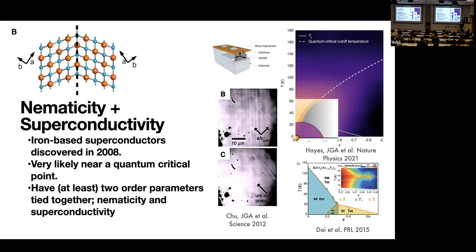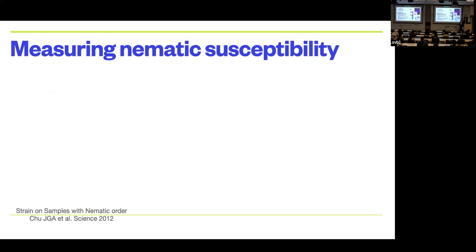But anyway, what was the broken symmetry? What was the order parameter? Well, we knew that the system was orthorhombic and it had this structural anisotropy. We thought this might be driven by an electronic anisotropy, and that's what we call nematicity, a label that we gave to anisotropic electrons in the system. So you can imagine that the electrons somehow want to have a preferred direction in the system, and maybe that's what was driving all the structural changes, and maybe that's the internal order parameter that was driving the superconductivity. And we characterize this by just the anisotropy in the electrical resistance. That's what this number here means, just the difference between the resistance in the A direction and the resistance in the B direction. That became a proxy for our order parameter, which is basically just the electronic anisotropy in the system.